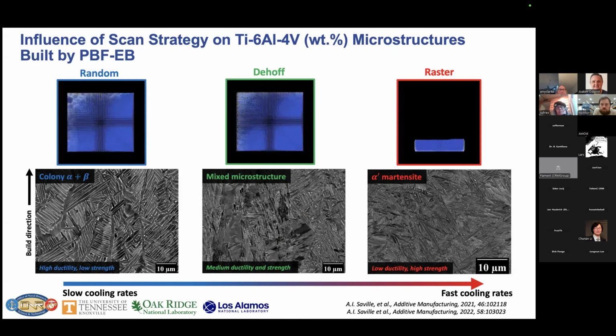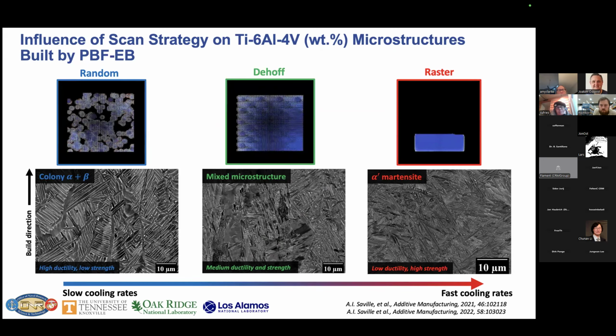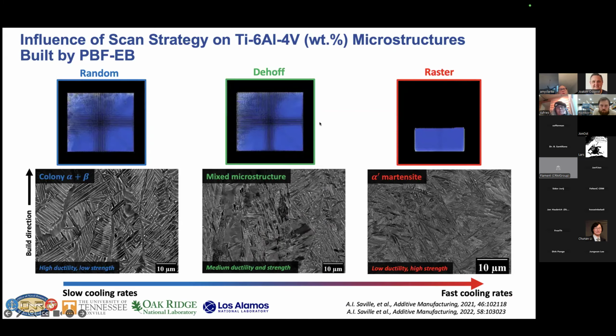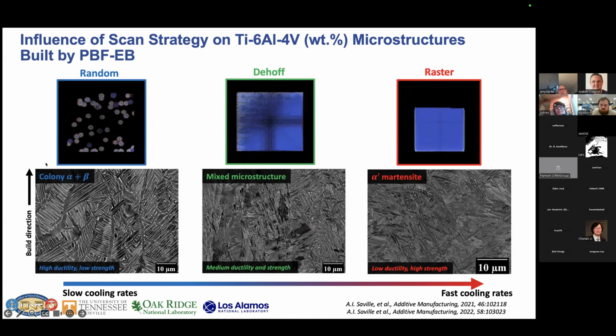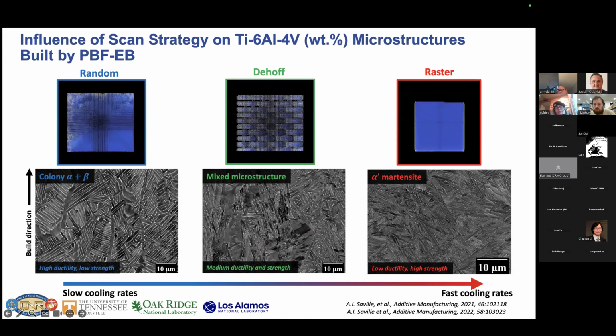We have done some work on Ti-64, which is really a ubiquitous alloy for aerospace kinds of applications. And here we've done work changing the processing conditions, so going from spot melts to a raster, and then the Dehoff pattern, which is something in the middle. And here we actually need to worry about solid state phase transformation as well. So we can see that slow cooling rates tend to promote more colony alpha beta microstructures, where with faster rates, we tend to get more martensitic kinds of microstructures.